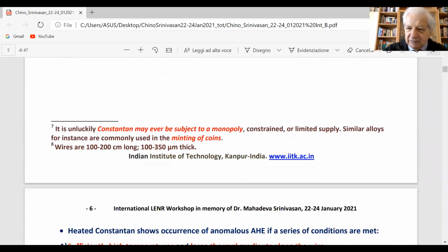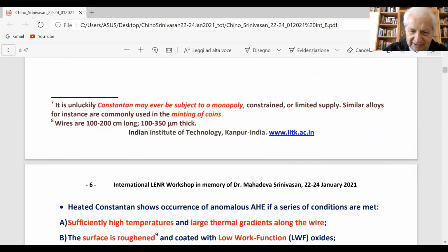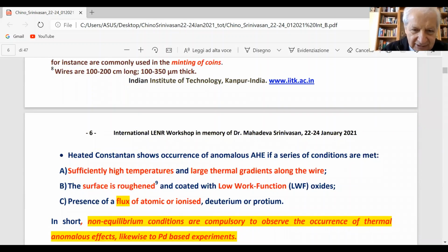In one experiment, we worked for about 1 year continuously. Usually with palladium, we can work 1 week, 2 weeks maximum before it breaks. So it is a very large improvement.